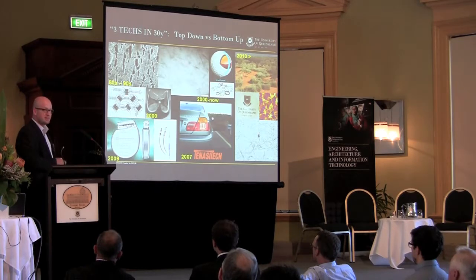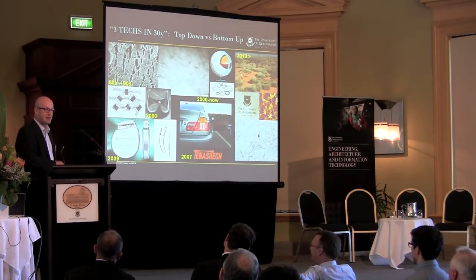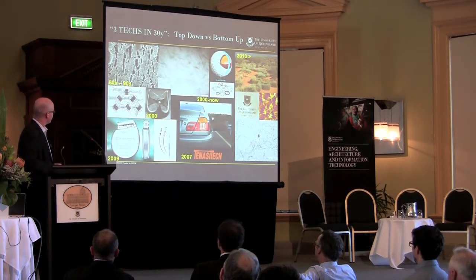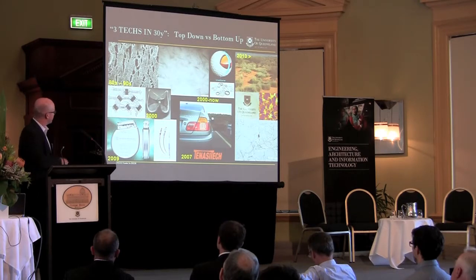If you dive down into these polyurethane rubbers, you have these rigid nano domains and these soft, flexible domains. If you add stress to that, they sort of stretch out in these areas, and these little areas, these soft segments as they call them, degrade. And you start getting this Swiss cheese type appearance, and obviously the insulation was failing and patients were getting into trouble. So we had a big program in the Cooperative Research Centre for Cardiac Technology to reformulate these materials and make them more stable.